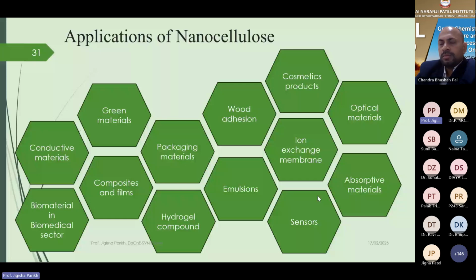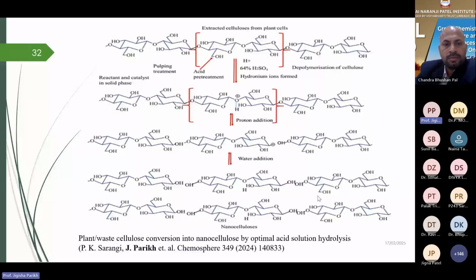So, the mechanism of the formation of this nanocellulose. As you know, cellulose is composed of a polymeric chain of linear 1,4 anhydro-D-glucopyranose according to its structural composition. The repeated building blocks of the cellulose molecules are illustrated by the anhydrous cellobiose, which is made up of two anhydrous glucose units. Each unit has three hydroxyl groups with distinct reactivities at the C2, C3, and C6 locations, which can help in establishing intramolecular and intermolecular hydrogen bonds. You see over here all these intramolecular and intermolecular hydrogen bonds, and they enable the development of a three-dimensional, highly structured crystalline structure.